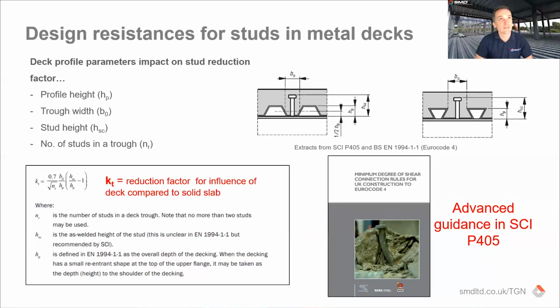Interesting question. That's from Kieran. Up to a limit, there is benefit, and clearly there would be benefit. I haven't got the numbers off the top of my head. I think what I would say is the code, due to how composite construction has developed, the types of studs used, the fact that slabs are typically shallow, once you get above a certain value, and we're talking really about a 100 mil stud for a TR60 plus or an R51 plus, whilst putting a 120 or a 130 stud will clearly give you more resistance, the codes are very much heavily based on testing, the primary amount, if not most of which, is based on a 100mm stud. So you're kind of going a little into the unknown in terms of being able to have an equation that could give you the values for that.